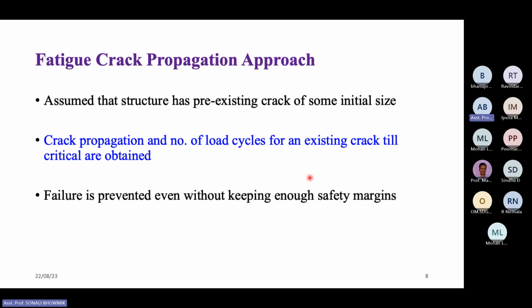So what do those fatigue crack propagation approaches do? Here we assume that the structure has a pre-existing crack of some initial size. This approach is based on the assumption that there is a pre-existing flaw or crack of initial size. Then, with crack propagation, you can find out the critical crack length and the number of cycles, all based on this assumption. And you can ensure that failure is prevented even without giving excessive safety margin. These are the things we want to explore here.